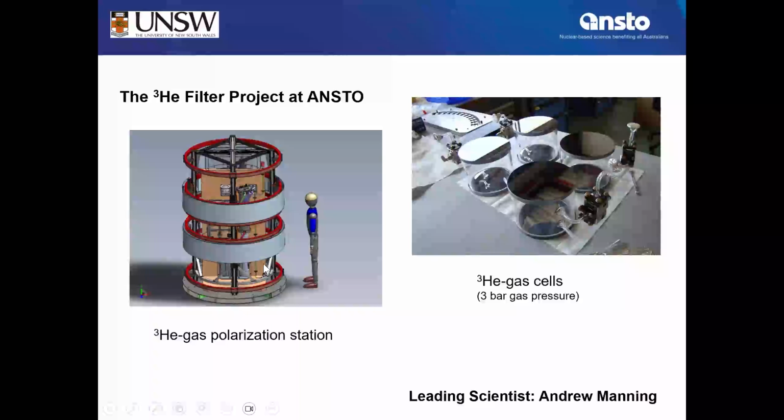So we polarize the helium-3 gas inside these cells, and then we can transfer these helium gas cells to the individual experimental setups. And after 12 hours, we have to replace them and kind of charge them up again. But as I said, it's an intermediate quantum state, lifetime of several hours, so 12 hours, it's pretty convenient. I think the entire setup cost more than $1 million.